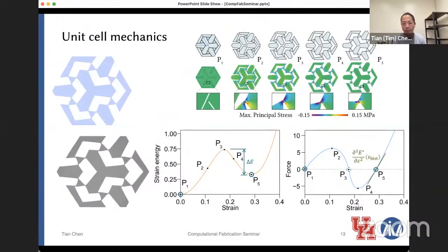The second we can optimize for is the slope at the second equilibrium state. This is exactly the tangent modulus of the system at that point, and this will give us as stiff a system as we need in the deployed state. So that's what we're going to use.